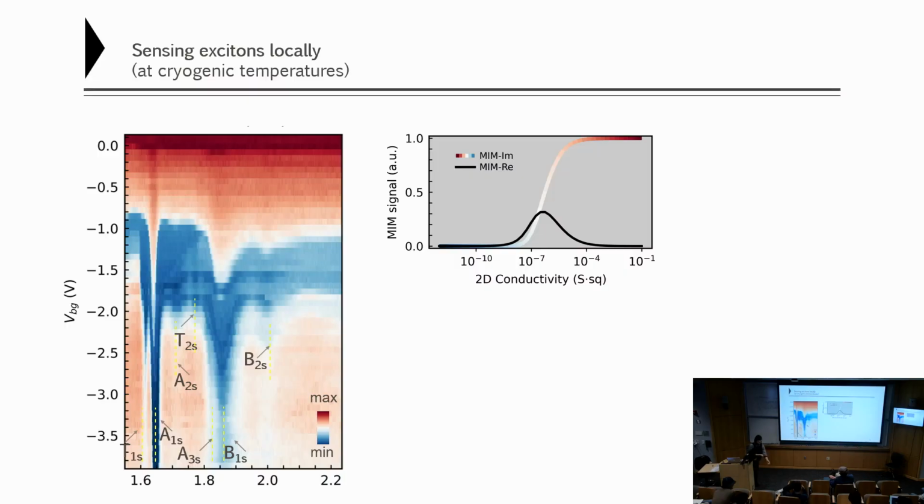So does this technique require you to have a band gap for your exciton? For example, if I have some semi-metal or something like that, does that mean this doesn't really work as well? Yes. I think for a semi-metal it would be very hard because in the background you already get a lot of reflectance of microwave. So you're somewhere here. And even if you excite more excitons, it might not show up very clearly.